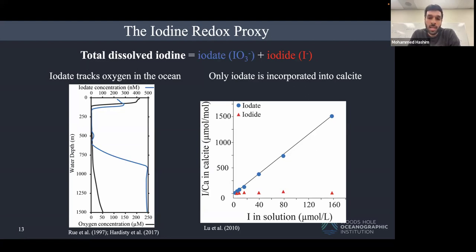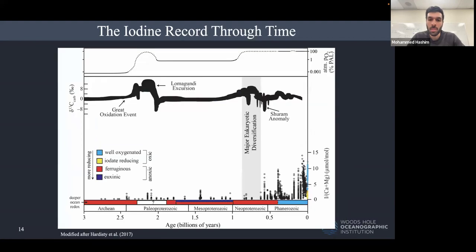And that means that if we take a mineral or a rock that is old and we measure the total iodine, if we see any iodine, the idea here is that it is iodate. So that means that the rock formed under oxic conditions. And if there is no iodine, then the rock likely formed under reduced conditions. And the important part that I want to emphasize here is that these were experiments where calcite was precipitated. So then people went back to the rock record and measured iodine, and usually iodine is normalized by calcium and magnesium, and this is what you see here in this plot.